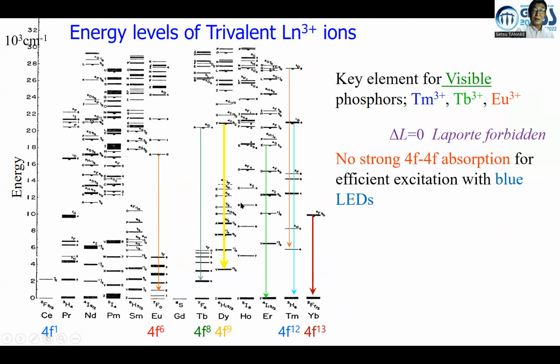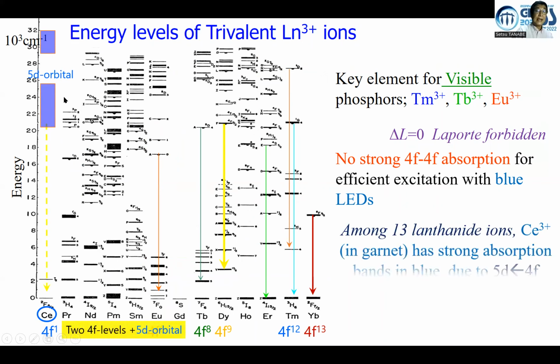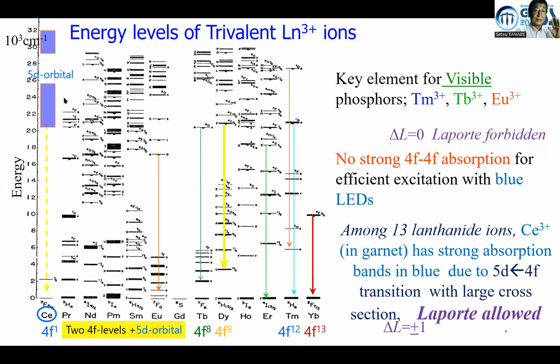So among various lanthanoid elements, f-f transition does not allow efficient absorption excitation, but instead, cerium has excited 5d orbitals in garnet host material. Garnet gives the largest crystal field splitting for cerium 5d orbital. And the good thing is f-d transition is Laporte allowed. So very efficient excitation by f-d absorption transition and large emission cross-section of short lifetime. Maybe typical excited lifetime of f-f transition may be millisecond or 100 microseconds, but that of YAG-cerium is 50 nanoseconds.